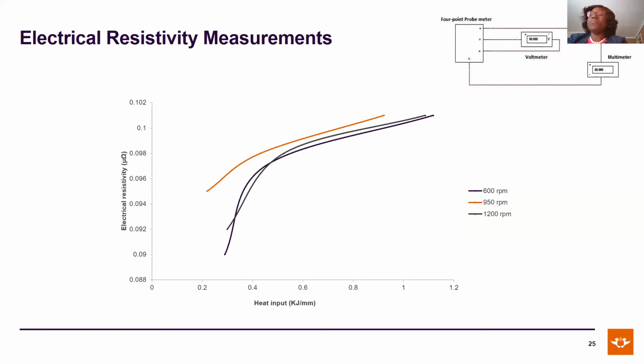We have the voltmeter, the power source, the multimeter, and then we place the sample with the 4-point probe meter, wherein we carefully placed 2 probes on aluminum and 2 probes on the copper, with the friction stir welded sample. So the result, the data obtained, is what I have in this graph here, which is indicating the electrical resistivity in micro-ohms compared to the heat input into the welds.